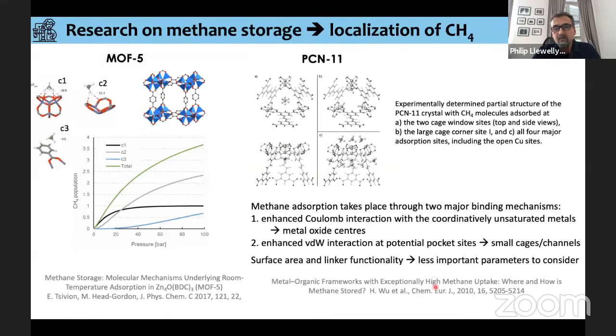Again, this is taken up in a previous study where the authors looked at a whole series of different materials. And this is just the result for a material called PCN-11. And we can see here the adsorption of methane in this site here, close to the metal centers there, or even here. And what is interesting here is the conclusions are that the methane adsorbs in two different areas via some types of interactions with the metal centers, but also if the cages are quite small, if they're side pockets, for example, within these small cages and channels. What was also interesting from this work is that the surface area or, for example, the linker functionality, we'll come to linkers later, are less important parameters to consider.